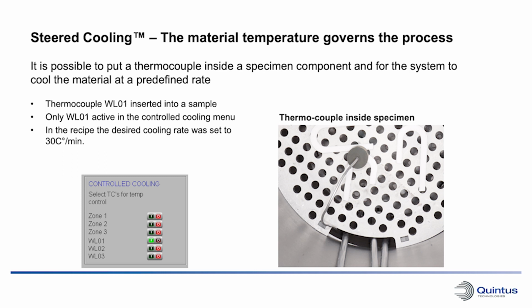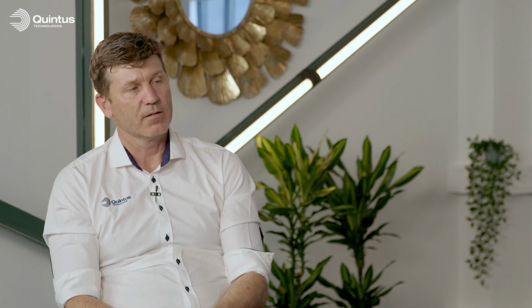Does that give opportunities then for modeling this, or to have a look at how parts behave in the HIP? Because the high pressure gas that we use circulates with natural convection during the heating sequence and also the soak time. But during the cooling sequence, we have a forced gas flow. Since you don't have any boiling or other complicated features that appear when we have a liquid as a quench media, it's very easy to calculate and know how the relation between the gas and the component, and the heat exchange, will behave.